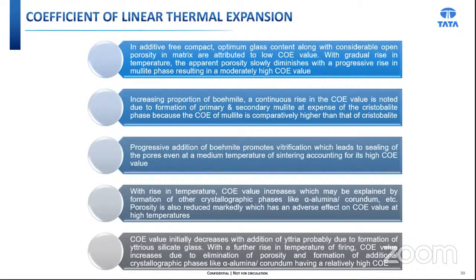Compacts free from additive, with optimum glass content along with considerable open porosity in the matrix, are attributable to low coefficient of expansion. But with increasing temperature, the porosity decreases and the coefficient of expansion value increases. When alpha alumina or mullite has been produced, the expansion value is increased because alpha alumina and mullite have a high coefficient of expansion value. If the porosity is reduced markedly, there is an adverse effect on the coefficient of expansion value at high temperature.